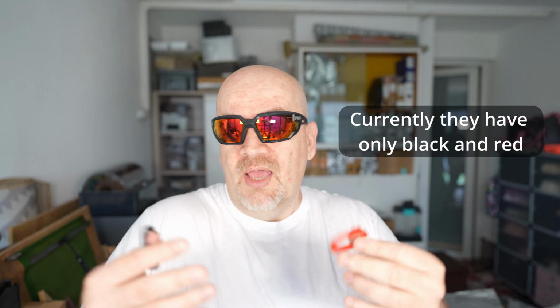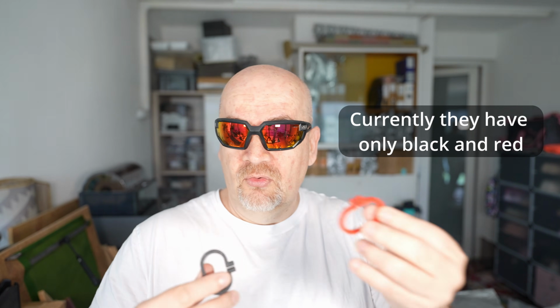The second, probably we can have a bigger option for the colors, because the glass fibers are transparent, and we can have, for example, this nice red color too. With carbon fibers we can have only some darker colors, if not black. And the third one, maybe it's not so important, but glass fiber can be dried or pre-dried in a microwave, carbon fiber not. With the PCTG I don't use this possibility too often, but sometimes I can speed up the drying process by pre-drying in a microwave, let's say 2 or 3 times 30 seconds, and then it can go for a much shorter time into a regular filament dryer.